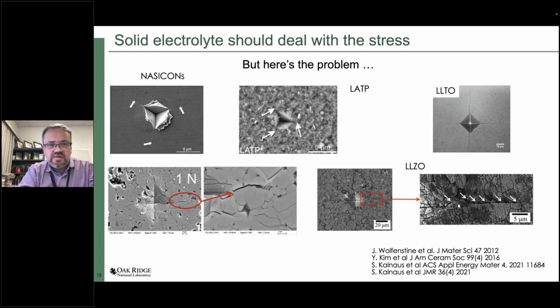The problem is that the way to deal with the stress for most of the solid electrolytes that we have, they're ceramics, right? So the typical response to the stress is to crack under pressure, unfortunately. These are examples of what happens to different electrolytes, from NASICONs to LLZO, when you introduce a sharp contact load into the electrolyte. The response is usually formation of a crack. That's their way to reduce the stress.